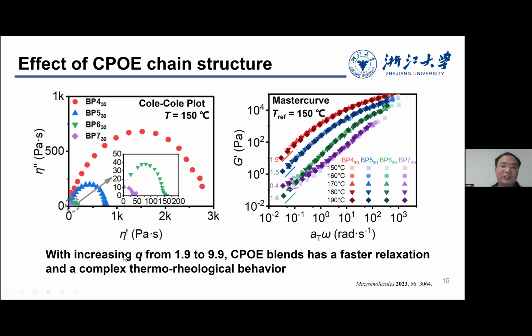And we also further studied how the chain structure affects the properties of the copolymers. We find that increasing the insert number from 1.9 to 9.9, the plateau has a faster reduction and shows complex thermo-rheological behavior. For example, if you check the Cole-Cole plots, you can see they become smaller as the Q increases from 1.9 to 9, the small diameter you see here. And also if you check the master curve, you can see the upturn with the increase of the branch number. So all this demonstrates complex thermo-rheological behavior.